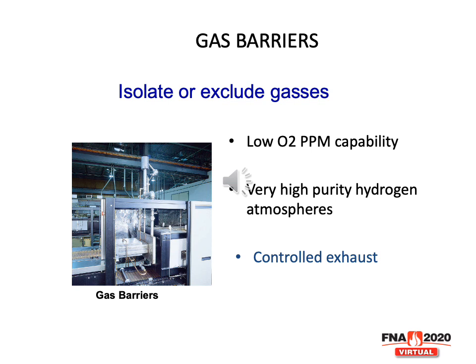We have a furnace that actually has nitrogen curtains on the end and hydrogen in the center, and we're able to approach 96% hydrogen in the middle of the furnace. For some processes that's very important. For others, you're happy enough to get into the 65 or 70 or maybe even 80% hydrogen in the oven. But there are some that require that very, very high purity hydrogen, again up into the 96% area.